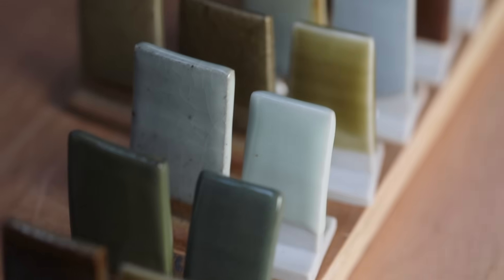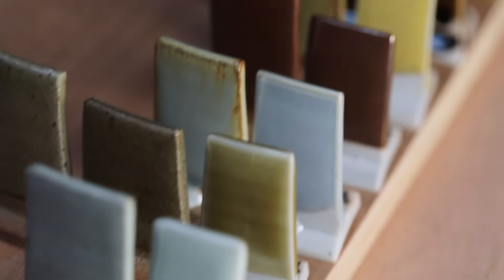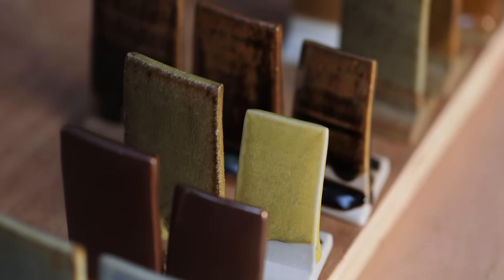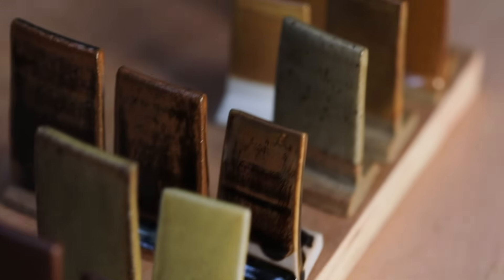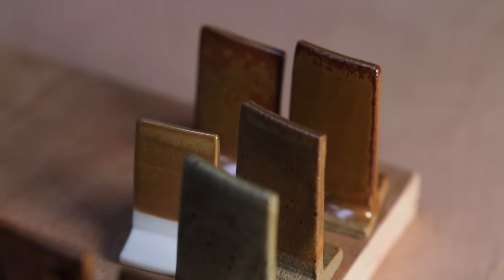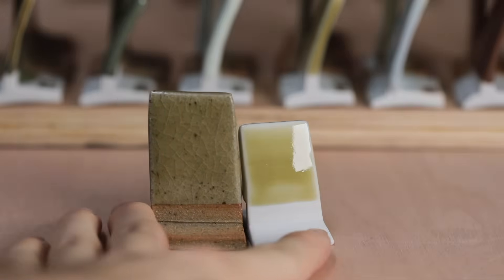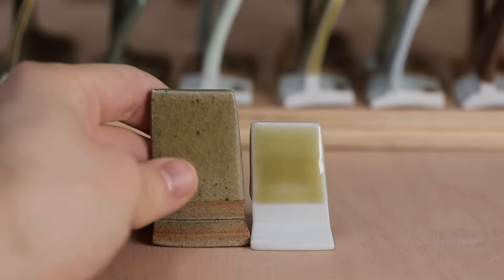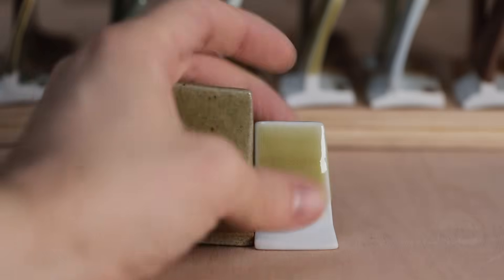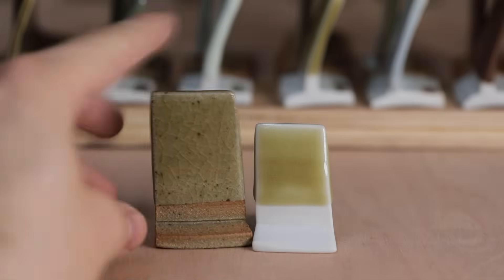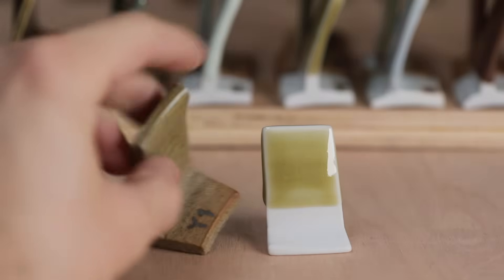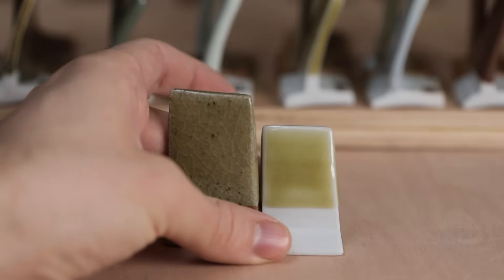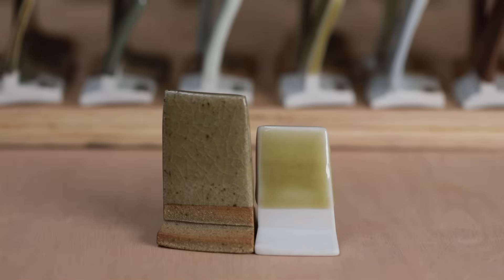And I did yield some really lovely tests, but whether or not I'll actually use them is another question. I ended up using a combination of both red iron oxide and titanium to get most of these yellow hues, which I added to various bases of my own, and to bases that I found on the wonderful website glazy.org, which I'll leave a link to down in the description below. I ended up with a multitude of tests like this, which were yellow but they were a bit dull. In general, I was using about 0.5 to 1.5% both red iron oxide and titanium to achieve these colours.